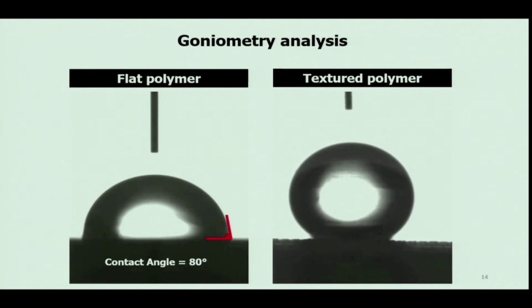For the flat surface, the contact angle measured was 80 degrees. And for the textured polymer, 138 degrees. And this was just the first test, without the optimized conditions yet. So I expect to have even higher degrees of hydrophobicity after thermodynamic optimization.